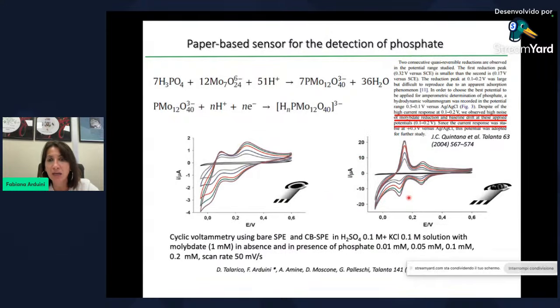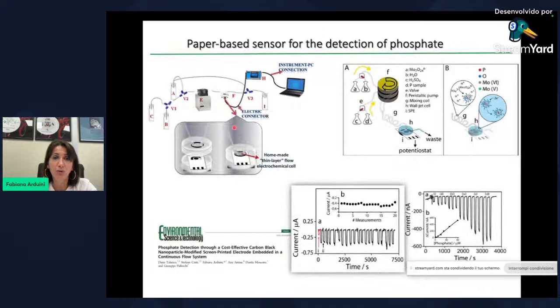In this case, again, we use carbon black as a nanomodifier of the working electrode surface. We demonstrated the utility of carbon black in our previous work using a paper-based sensor. This is the response without the modification of carbon black, and so better peak resolution, and the sensitivity goes from 2 to 20 in the case of the electrode modified with carbon black. And also we are able to work at lower applied potential, because using carbon black, it's possible to work in the first couple peak without fouling problem. And we demonstrated this also in the case of flow analysis.